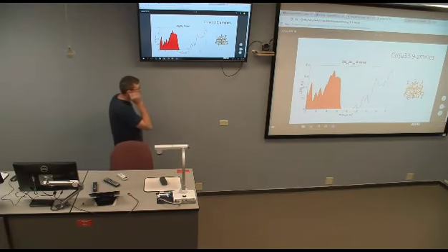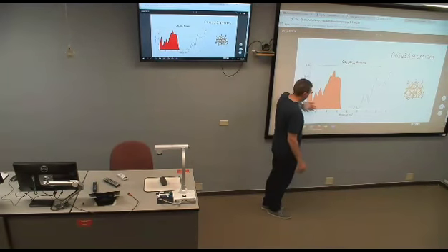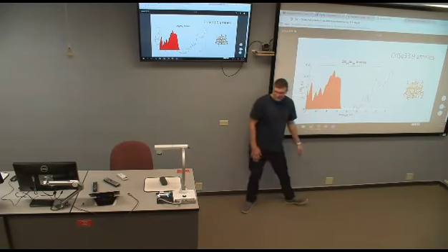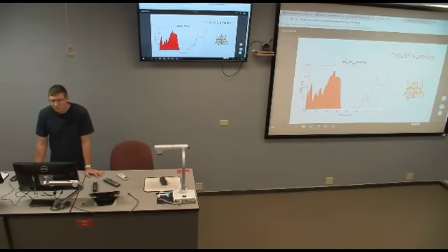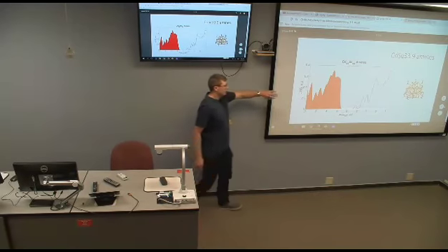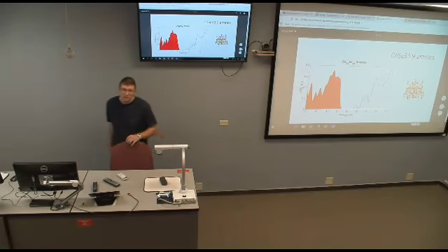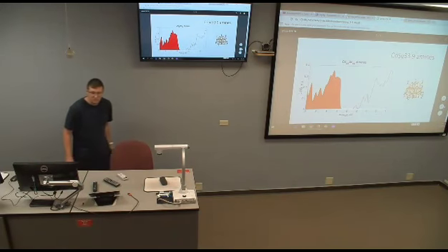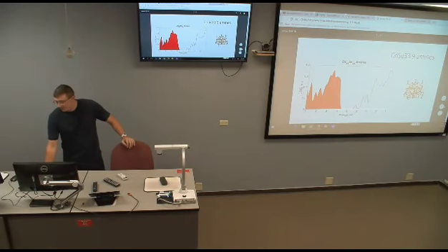So as a base, looking at some of the electronic structure of just the small quantum dot itself, a similar feature found in most of these, you're going to see the edge of the valence band, and then just below the conduction band, you're going to see a little bit of an unoccupied state. Which functions, what exactly are you showing to us? So this was done using VASP, a PBE functional with plane waves for the basis. One of the issues that we had talked about before was having a reduced gap in the system itself. So this is just the quantum dot itself.